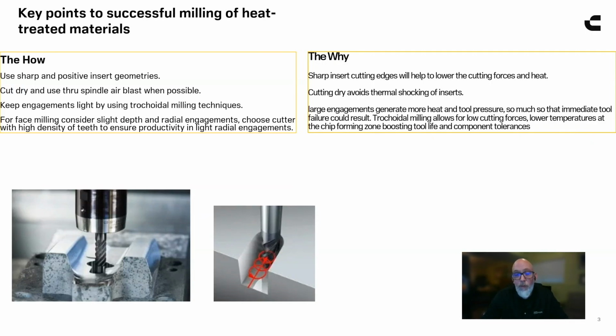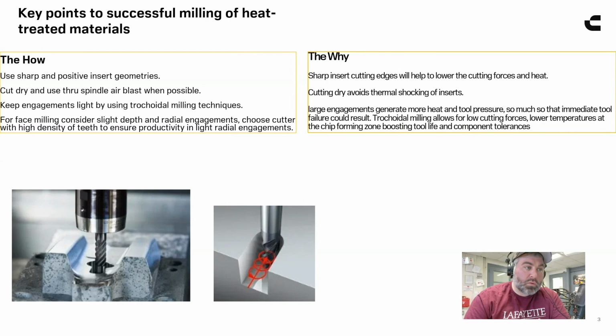And so what we found is by running air, the tool gets hot, but it's regulated. And it stays at a constant temperature. It avoids the thermal cracking that we see along the cutting edge. Once that thermal cracking starts, you really start to deteriorate the cutting edge right away. And in these types of materials, you've got to have that sharp edge to keep the heat down. So it's like a runaway train at that point if you're not controlling it.